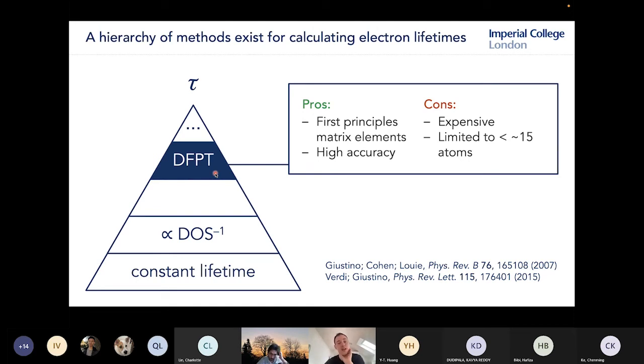And they're extremely accurate, and they're fully first principles methods. We can really see mobility and transport properties within about 5% of experiment using these methods. So they're great, but the downside is that they're extremely expensive to run. I'd say that for most practical calculations, you're probably limited to less than 15 atoms in the unit cell. You can go higher, but it's going to cost you a lot of computational time.